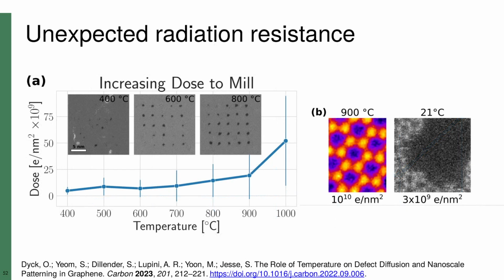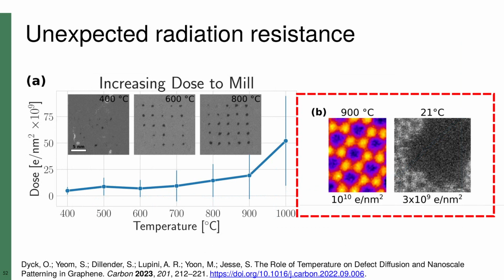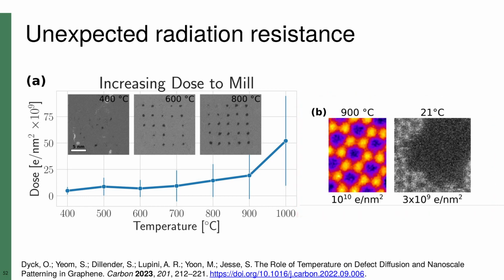Perhaps a better illustration of this effect is shown here. We are comparing an image acquired at 900 degrees Celsius that delivered a dose of 10^10 electrons per square nanometer during the acquisition. There is no observable damage to the graphene. In contrast, this image was acquired at room temperature with an order of magnitude less dose, and the graphene is almost completely destroyed. At first we considered that it could simply be healing.